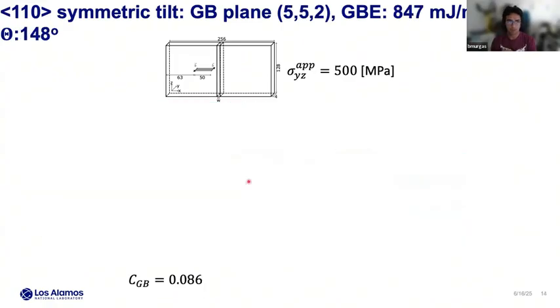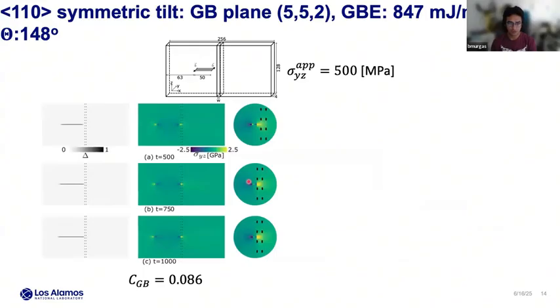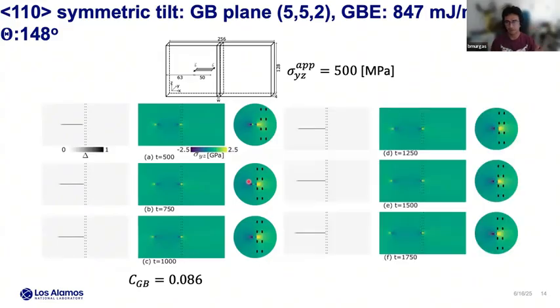For the other case, where we have higher grain boundary energy, a different grain boundary plane and misorientation angle, you will see a different effect. The dislocation starts to approach the grain boundary, it gets compressed, but this time it gets pinned at the grain boundary. The main difference between this grain boundary and the previous case is that this one has a higher grain boundary energy. So you can see the effect of the grain boundary energy for a metastable state, and we can predict that. We performed several simulations from a molecular dynamics data set of grain boundary dislocation interactions, and we can predict the behavior of several states.